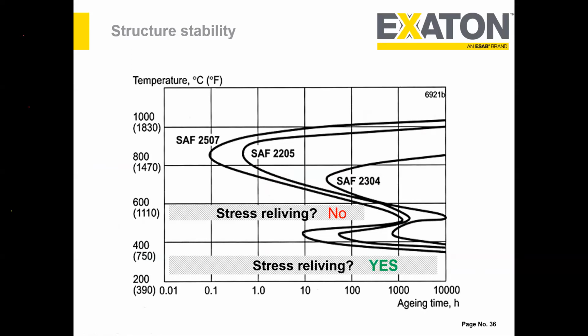The higher it goes, the ferrite phase has the potential to transform into sigma phase. So definitely no. If it is really, really required, then it can be done at a lower temperature, let's say 300 degrees centigrade, for a longer time period. That will avoid such kind of C curves, and we can actually eliminate the residual stresses.